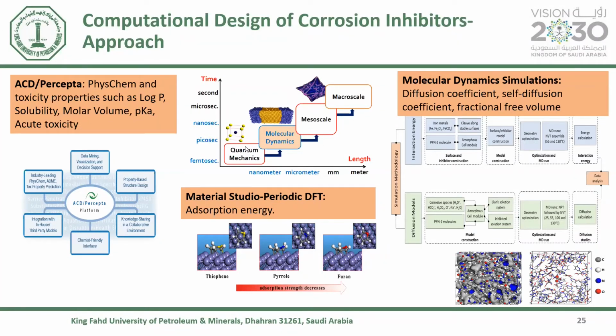We could also look at the interaction of the molecule with the surface of the metal at the atomic scale using quantum mechanics, which we call DFT calculations. It can furnish us with adsorption energy and some electronic properties of the molecule-surface interaction. So this can be like a property of the molecule, like the adsorption of the molecule on the metal surface, which is very important for corrosion protection. If you could determine the adsorption energy of the molecule on the metal surface, it can give you a descriptor that can give you a clue of whether the molecule will inhibit corrosion or not.